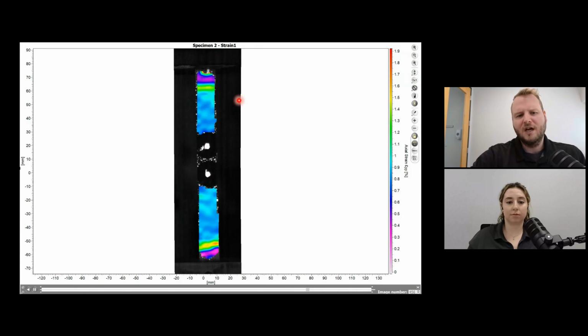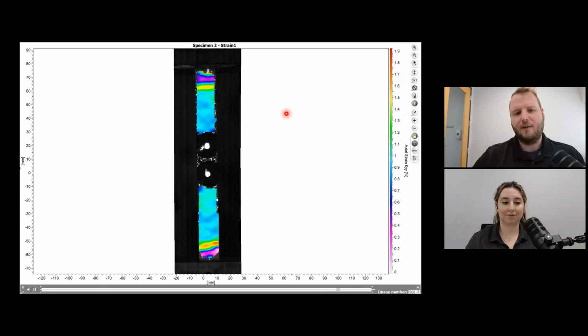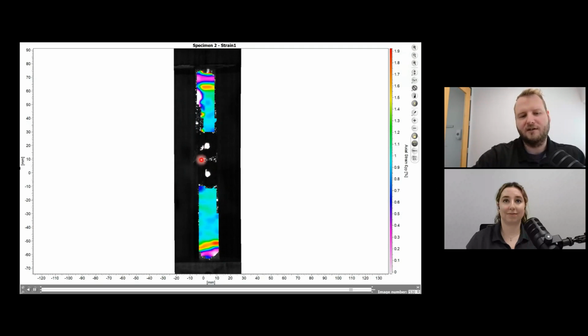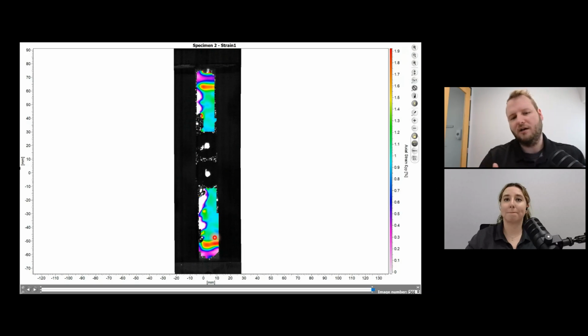With this one, I think this is the exact same tabbed specimen that Ashley was using. And you've seen that every time that specimen failed at the tabs. Now you can see what was actually happening there. We're taking that strain reading here, and if you were to use a traditional clip-on extensometer or just the AVE with the dots, you would be unaware of what is happening here. I think everybody can imagine that you have the tabs sticking out a little bit too far, and then they're peeling back and influencing your specimen. That's what it looks like over here.